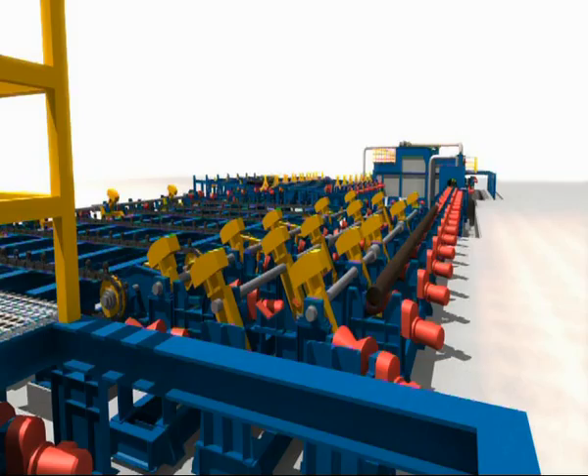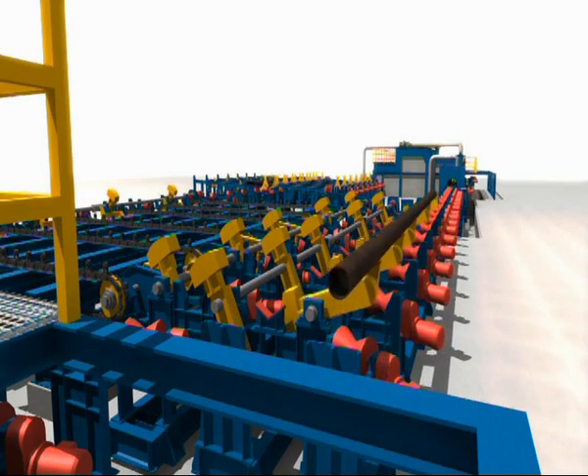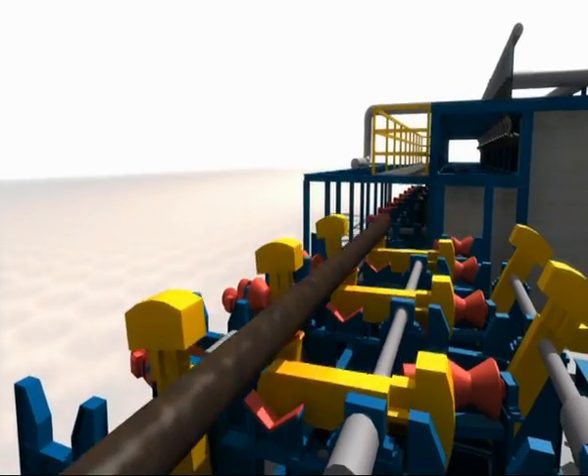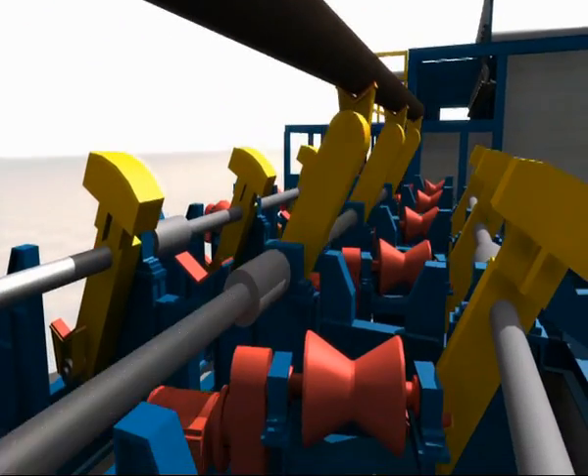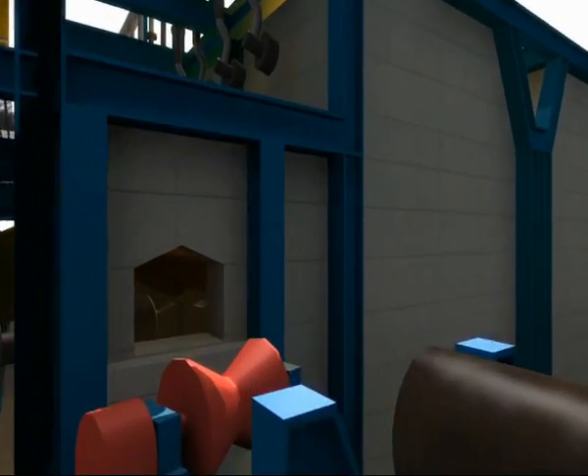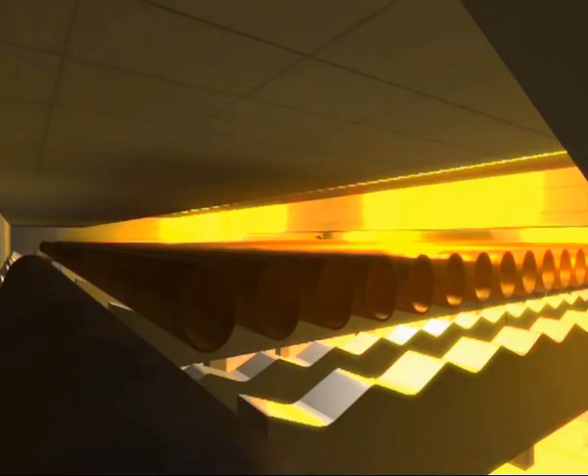The adoption of this engineering solution is aimed to guarantee the highest percentage of austenite martensite transformation, even in thicker pipes, which is essential to obtain the consistent mechanical and structural characteristics required along every pipe and from one pipe to the other. The operation begins with the loading of the pipes on the inlet table of the line to be fed into the high-temperature furnace, about 900 degrees centigrade.